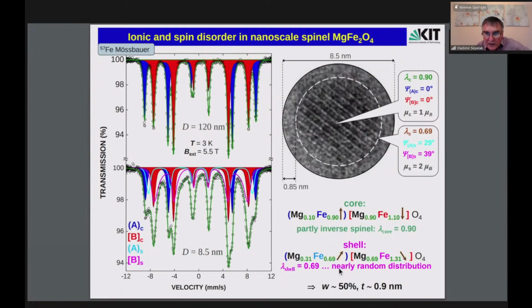We have observed nearly random distribution of cations with degree of inversion close to 2/3, 0.69. And also from the intensity of this second to the first line, we calculated the spin canting angle, about 30 or 40 degrees for tetrahedral and octahedral iron cations in the shell.